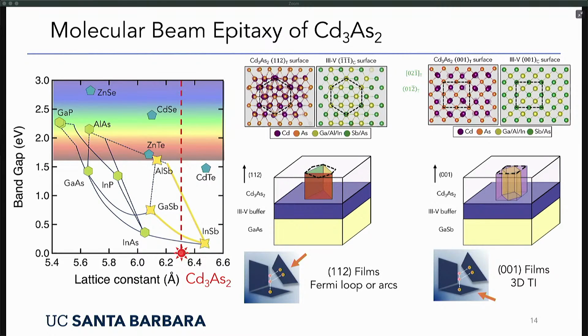The equivalent lattice parameter is 6.3 angstrom, and you can see that this is rather large for the typical 3-5 semiconductors that we have. To mitigate the very large lattice mismatch with substrates such as gallium antimonide, we very often grow lattice matched buffer layers, but I'll show you some of the problems with those. So it is generally not easy to grow the 3-5 semiconductors that we are using here as substrates and buffer layers with these lattice parameters.